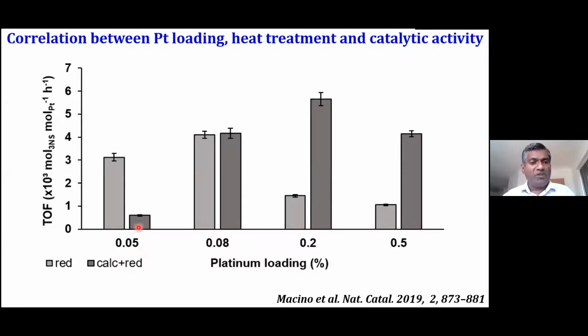For 0.05 loading, the reduced only catalyst is much, much more active compared to the calcined plus reduced catalyst. On the other extreme, if you increase the loading tenfold, to 0.5 loading, the calcined plus reduced sample is much, much more active compared to the reduced only catalyst. And we know for sure higher loading means A-SMSI is predominant.